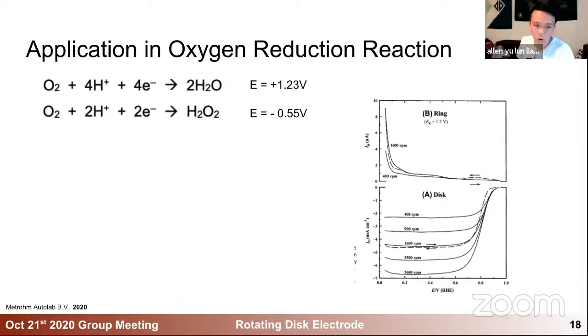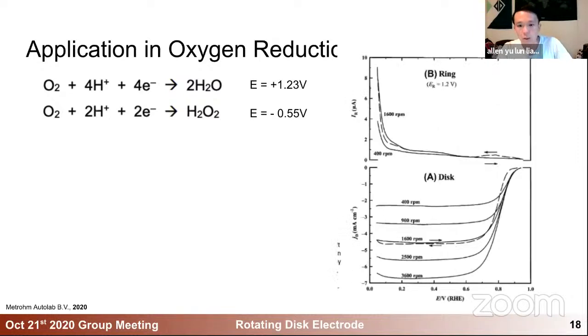And fortunately, these two reaction pathways have different reaction potentials. So on the disk, you can just do whatever you want on your catalysis. On the ring, you can apply a backward voltage, say an anodic voltage that is large enough to oxidize hydrogen peroxide back to oxygen, but not anodic enough to start splitting water into oxygen. Commonly applied is about 1 volt versus RHE, and that is definitely large enough to oxidize hydrogen peroxide.